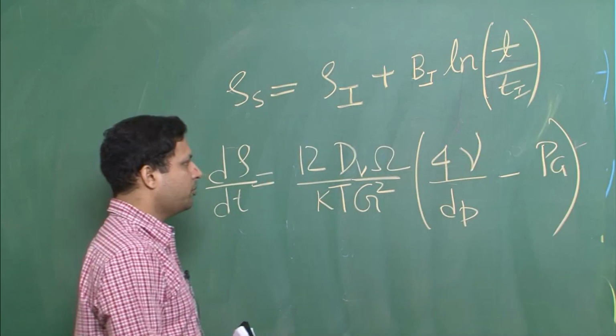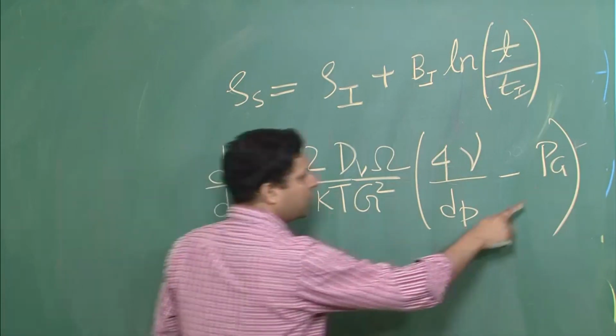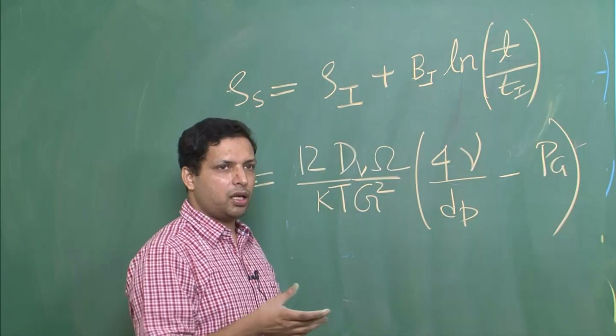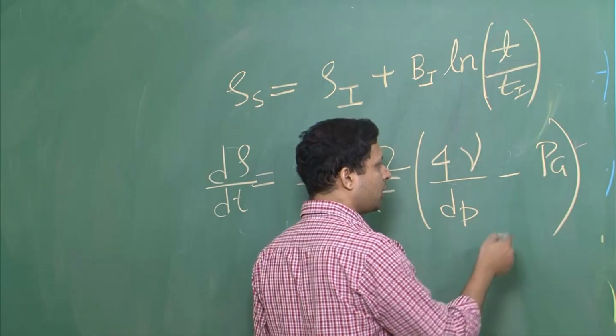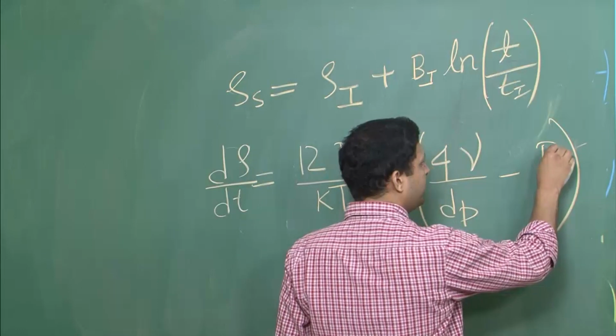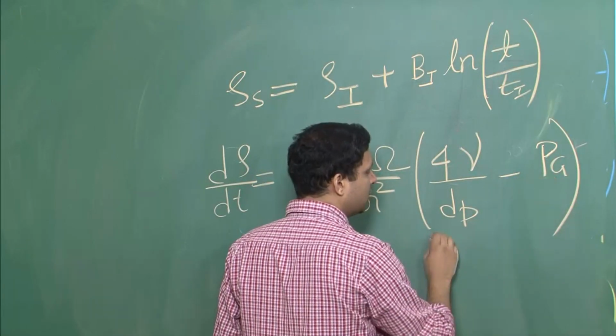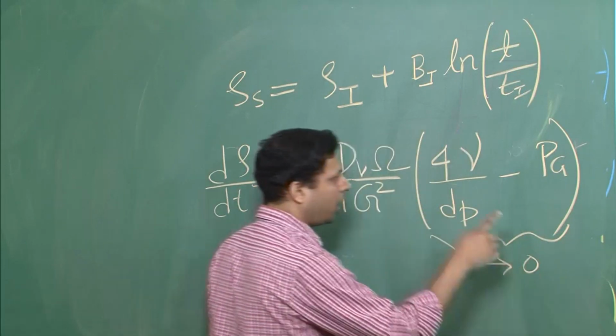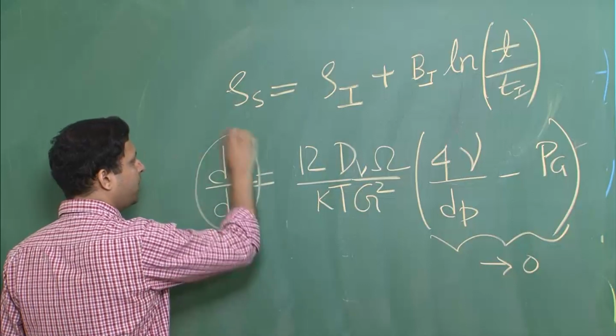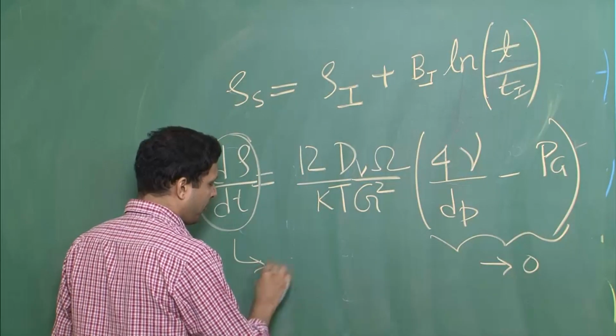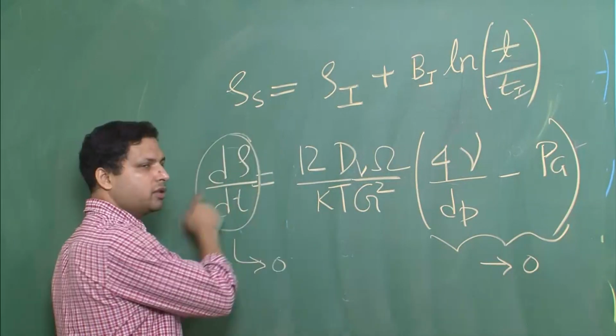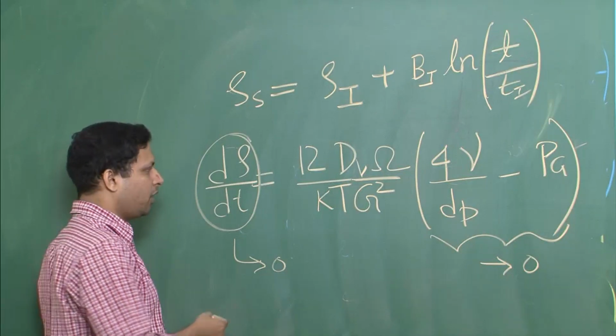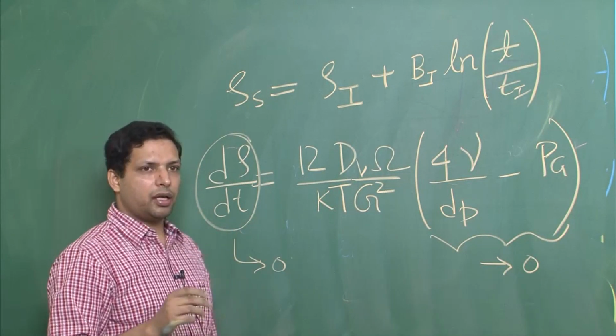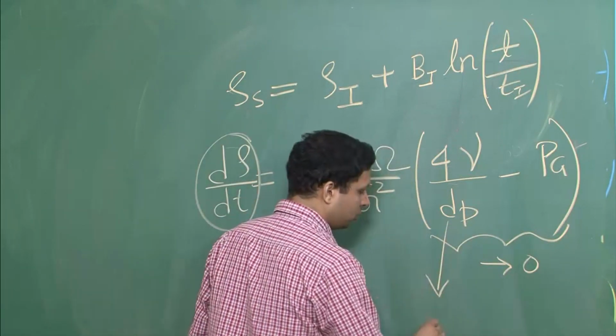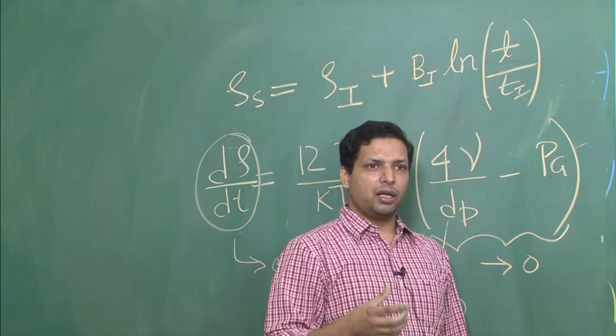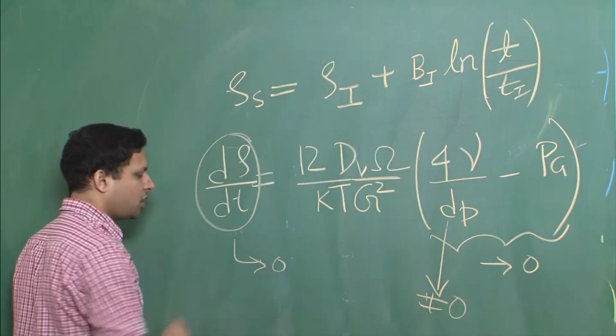Now the first and most important thing you will see here is that if you keep increasing the pressure, that is, if sintering is being carried out at high pressure, then Pg will keep increasing, and at a certain point this whole quantity may reduce to 0. And what will happen when it reduces to 0? d rho by dt becomes 0, meaning there will be no more change in the density. The shrinkage rate will not move any further, and the density will remain constant at that point. Although dP may not be 0, meaning the pore diameter may still have some finite value, your rate of densification may come to 0.